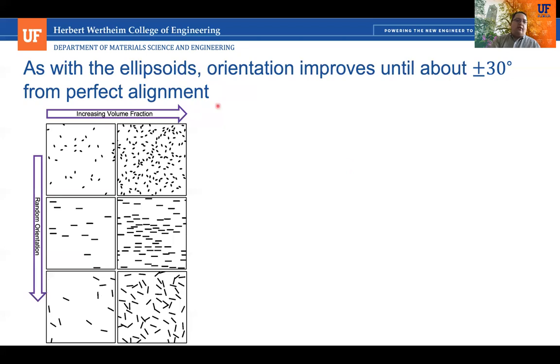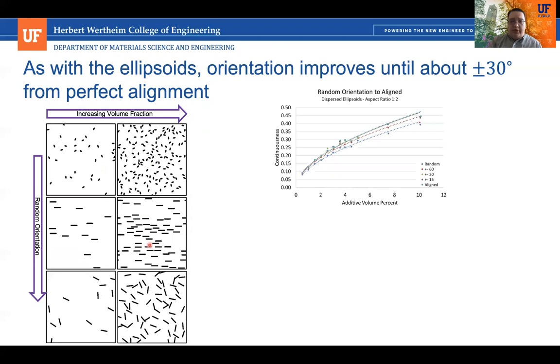So we first looked at dispersed particles where they have different aspect ratios. And so the orientation now matters. And the orientation could be random, or it could be all oriented in the direction of heat flow. And so they're very lined up. And we looked at ellipsoids, and we also looked at rectangular particles. So if we look at ellipsoids, and we look at the continuousness, which is directly impacting the thermal conductivity, the first thing that we see is that random distribution of particle orientations gives us the lowest effective thermal conductivity.